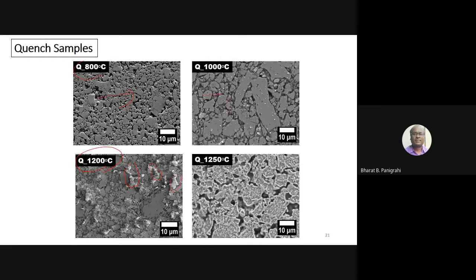This is a quenched sample, just when liquid started forming. The white spot you see is the region where liquid starts. You can see that hazy structure when the liquid phase appears. And at high temperature, you can see very clearly that at 1250 degrees, a good amount of liquid is formed and wetted all the grains.